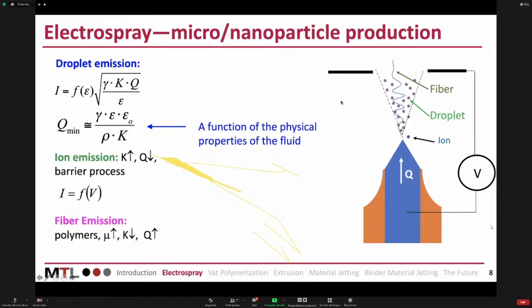And finally, if you do fiber emission, you're dealing with liquids that are basically mixes of solvents with long chain polymers. And in this effect of producing the jet, from the cone you emit a jet and the jet breaks up into droplets, for example. So from that stretching of the liquid, you can actually get fibers, and by hydrodynamically stretching them, you can get down to nanometers. So this is an opportunity to make nanofibers. So you see, it's a very comprehensive method, very simple.